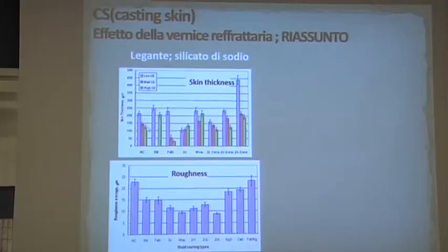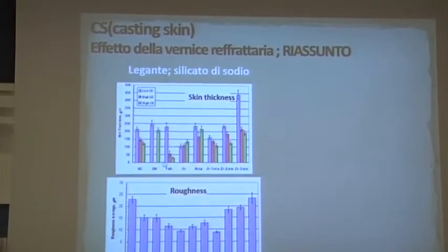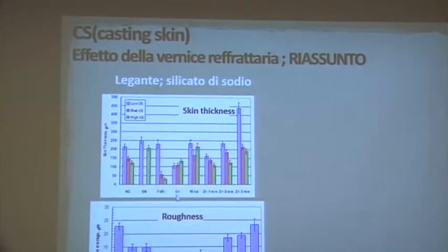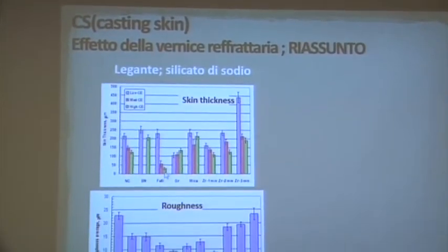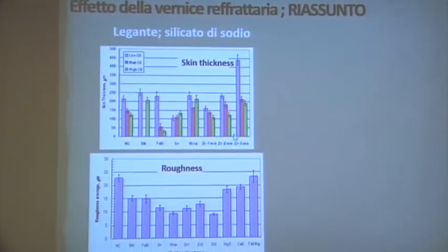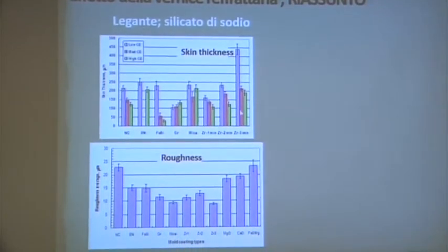So this is a summary of all the mold coatings on skin thickness, and this is for 3 different carbon equivalents: low, medium, and high. And you can see first of all that as you increase the carbon equivalent, you decrease the casting skin. And then the most efficient for high carbon equivalent is ferrosilicon. And you can see that the zirconia is not very effective.